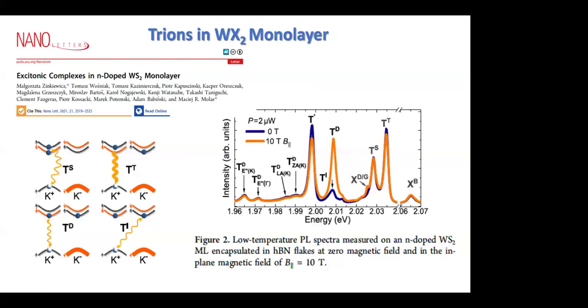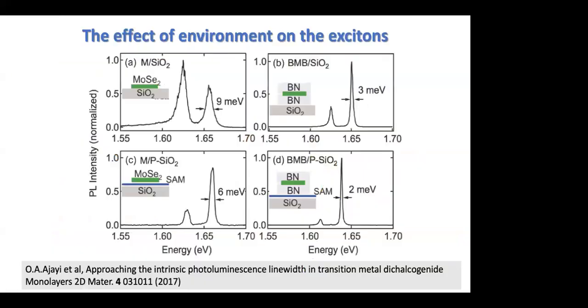So the story of excitons in those monolayers is really endless, and from time to time people are referring to new quasi-particles, new excitations. But this is possible because of some other achievement, and this achievement is the observation that the spectra of those monolayers can be greatly improved if the monolayer itself is encapsulated, we call it encapsulation, in between the layers of boron nitride.